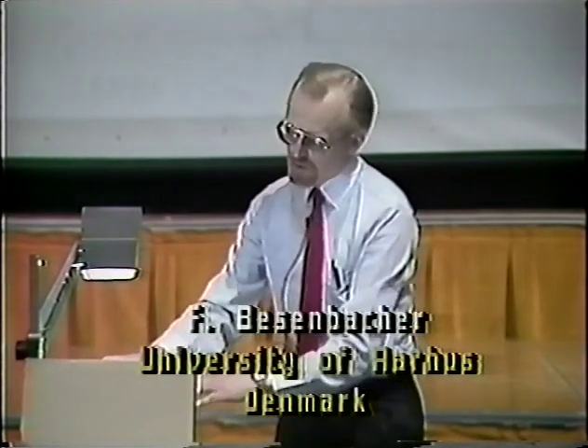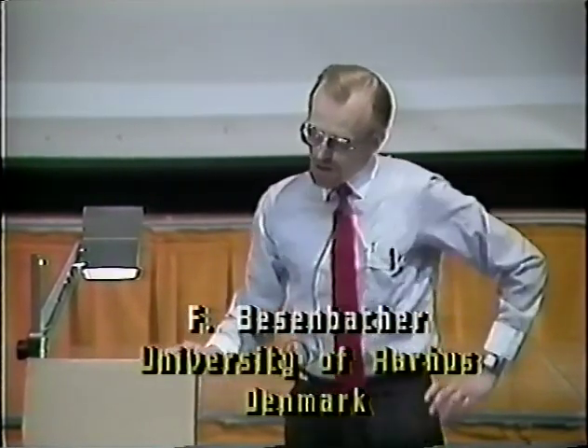Let me then go to our experimental studies. I said that was a combination of ion beam analysis techniques and ion implantation techniques, where we had tried to pick out certain conditions which are fairly easy to understand, so we can extract trap binding enthalpies and information on where the hydrogen is sitting in certain lattices. What we normally do is that we implant deuterium at low temperatures at an energy of the order of 15 keV, which ends up at a range of the order of 1,000 to 1,500 angstrom. Then we probe the deuterium by bombarding the crystal with 750 keV helium-3 ions, which gives a nuclear reaction, and we then detect either the protons or the alpha particles with a solid-state detector.